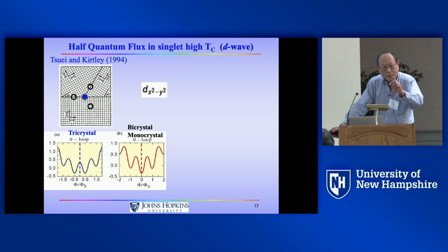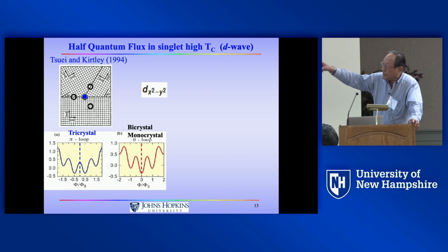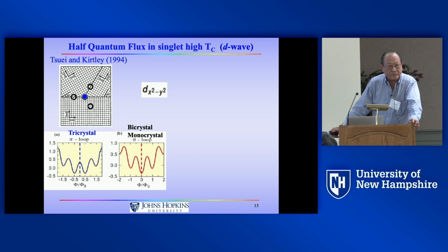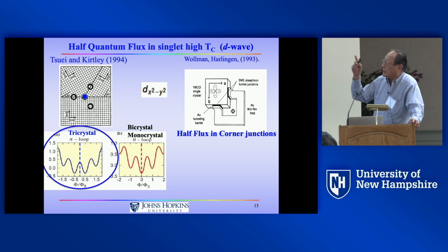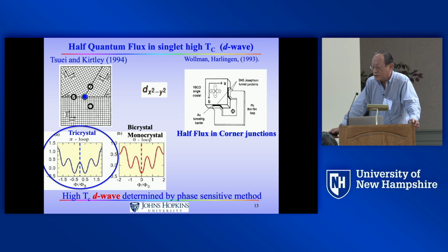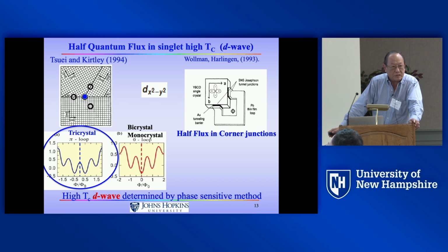In fact, the half quantum has actually been observed. If you are old enough like me, you went through the high Tc days. Tsuei discovered d-wave using exactly this theory: make a tricrystal, and at the apex you will see half quantum. Van Harlingen in Illinois made a corner junction with 90 degrees. They also saw half flux. So we need to remind ourselves, high Tc d-wave was not determined using thermodynamic measurement. It used phase-sensitive measurement. That is the reliable method, not thermodynamics.